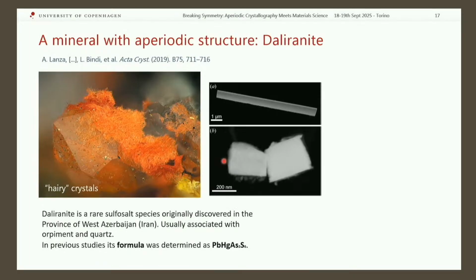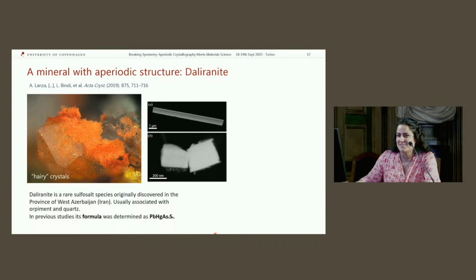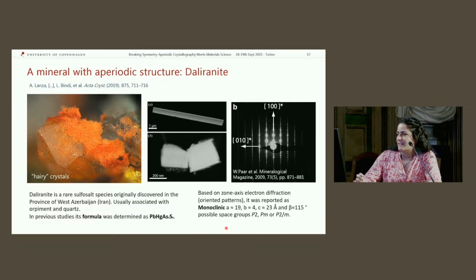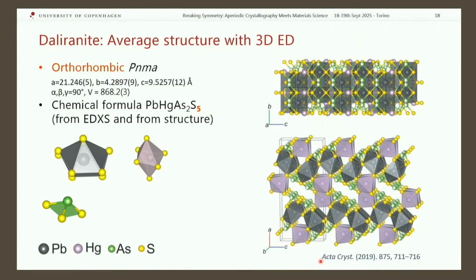When we look at these crystals in micrographs, we see that we have a well-formed crystal, but the well-diffracting domains are actually smaller than a micron. You see several hundreds of nanometers. This mineral, I didn't say, is called daliranite, and it's a nice blend of lead, mercury, arsenic, and sulfur, so tasty. It was previously analyzed with selected area electron diffraction, and we see that it diffracts very well. And a unit cell was proposed from this. But still, to solve the structure, we need to do three-dimensional electron diffraction.